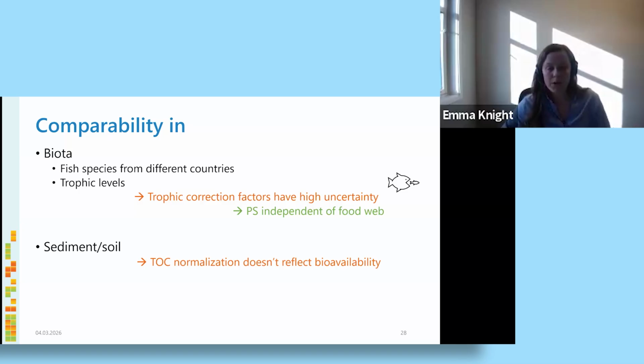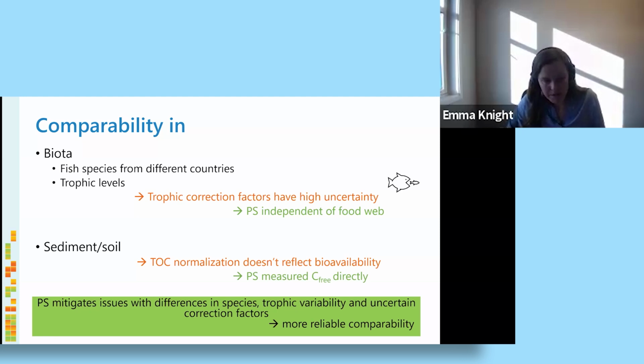So then we also can see the same thing in sediment and soil monitoring, where they're usually compared based on a normalization of the organic carbon content, which doesn't reflect bioavailability. So you might have a soil or a sediment that has a very high organic carbon content, but the exposure in that soil is actually very low. Therefore, comparability doesn't reflect bioavailability. And this is also where passive sampling can be very beneficial, because it measures this freely dissolved portion directly. So passive sampling mitigates issues with differences in species, trophic variability, and uncertain correction factors, giving us a more reliable comparability, and that's more in line with the Water Framework Directive.